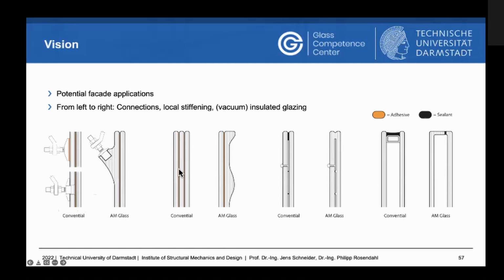When we want to stiffen out glass plates, this is the traditional way we're going. We're just adding more layers of a laminate. With printed glass, we can follow the stress trajectories or just be smarter about where we add our material to stiffen out. Then we have insulating glass units, in particular vacuum insulating glass, where a big challenge is the edge connection of the different glass panels. Here we could harness our printing process basically as a welding process, or even in bigger constructions where we need a spacer and a sealant, we could print around the corner and then have much less sealant needed here.